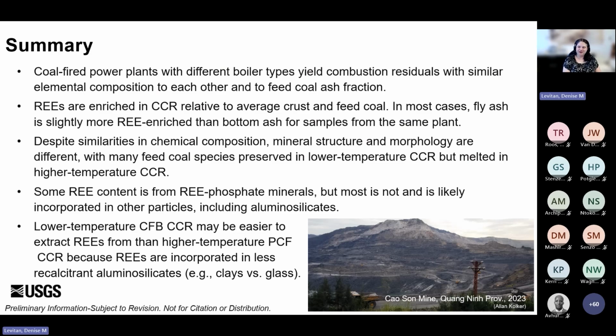And just to go back over the high points. So we had these two coal plants that had different boiler technologies. They were burning almost the same feed coal without too much stuff added in, pretty similar. And then the CCR produced by both of these plants had similar bulk chemistry that was reflective of the feed coals. So similar both to the coals that went in, but then also to each other, the two different plants. And they showed rare earth element enrichment relative to both the original coals and to upper continental crust general geology. So those were similarities, but then due to these different operating temperatures of these two different boiler types, we saw different mineralogy within those two different CCRs, which might mean that different extraction technologies could be applied to the PCF CCR versus the CFB CCR.